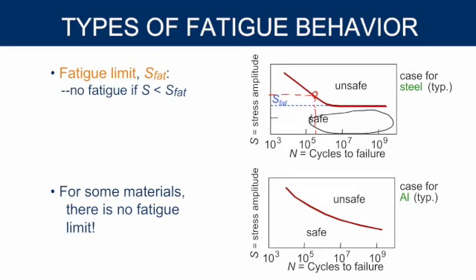So if I stay below a certain stress, that material will not fail. But most materials, eventually, they will fail due to fatigue, such as this line below. This would be an example of aluminum. No matter what that yield stress is, if I put enough cycles on it, it will eventually reach the line and cause a failure. Okay, so that would be aluminum has no endurance limit, and steel does.